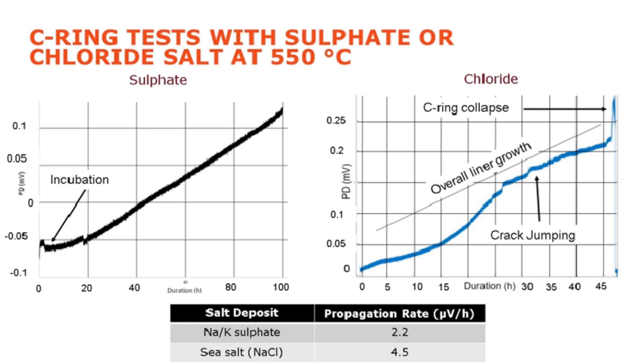They have comparable test conditions, other than they're using different salt deposits, so a different composition of the salts. The one on the left is sodium potassium sulfate based salt. We can see an incubation period, so the crack hasn't started straight away, but then it initiates and continues at a very linear rate, not really showing much correlation to the crack size as we would expect to see with fatigue, fairly linear rate trundling along.